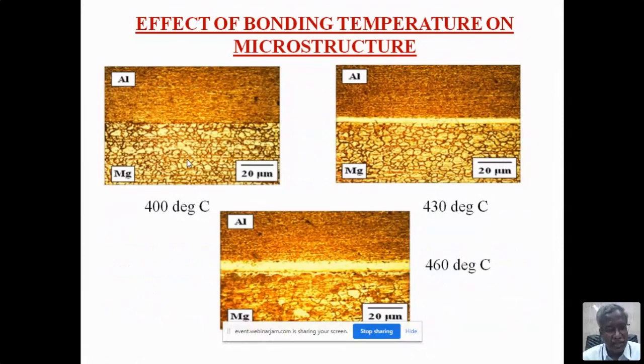The density is almost the same. Aluminum alloy is 2.7 and magnesium alloy is 1.7. Melting point, magnesium alloy is 600 and aluminum alloy is 650 degrees centigrade. It's also similar, but the main problem, which does not allow the materials to join, is the crystal structure. The crystal structures are different, so they are not compatible. So diffusion bonding is one viable method to join these two.